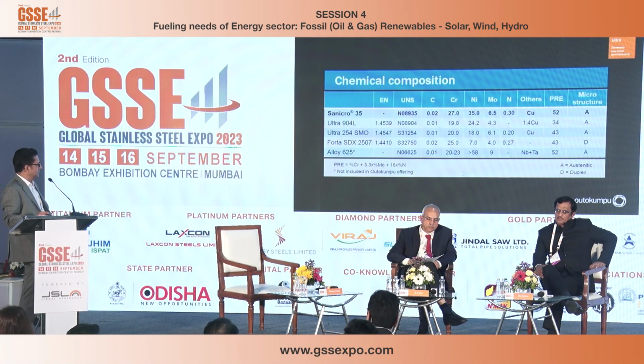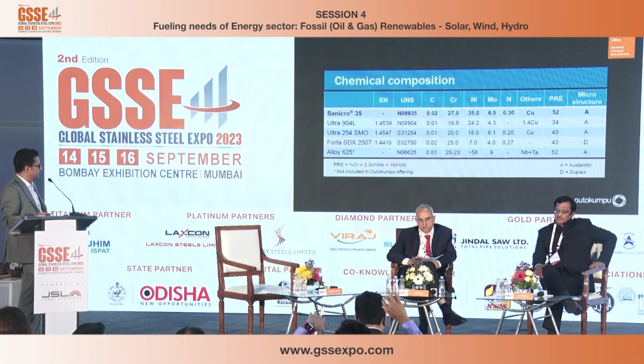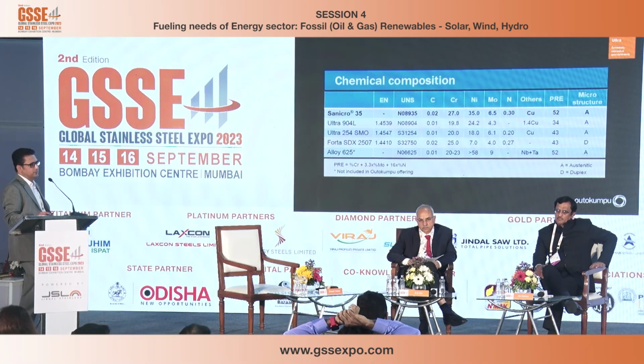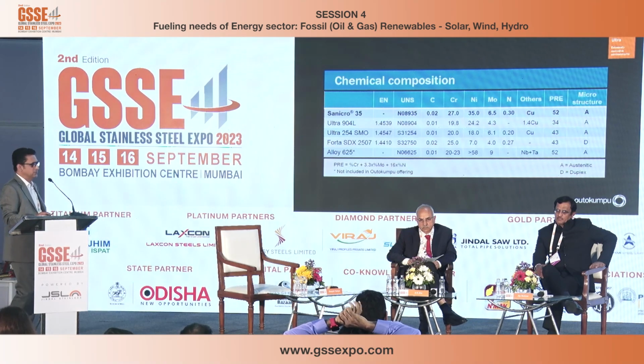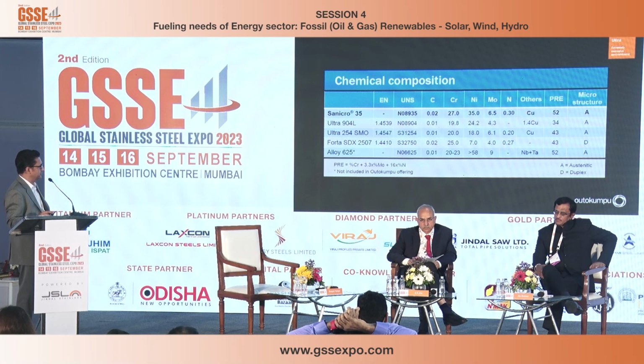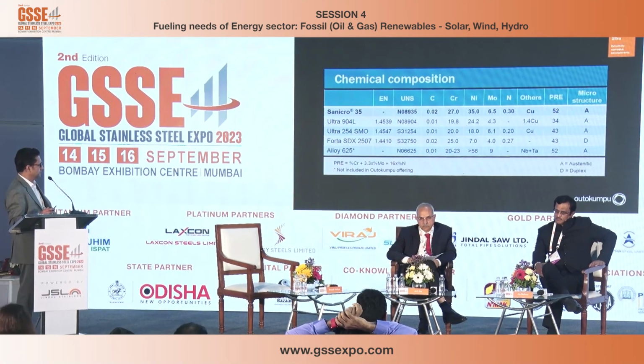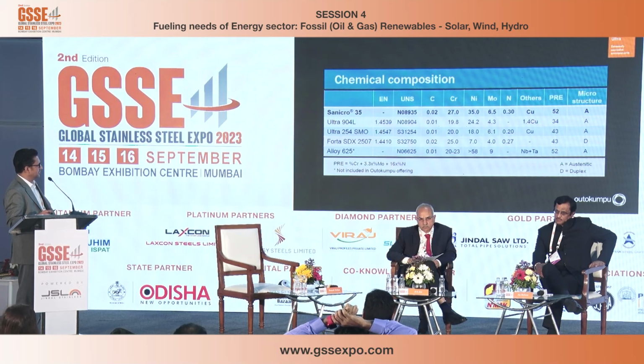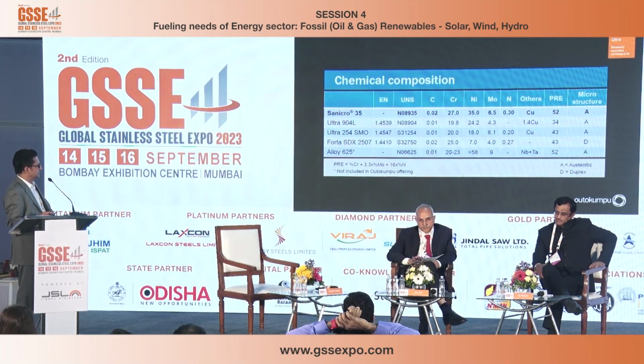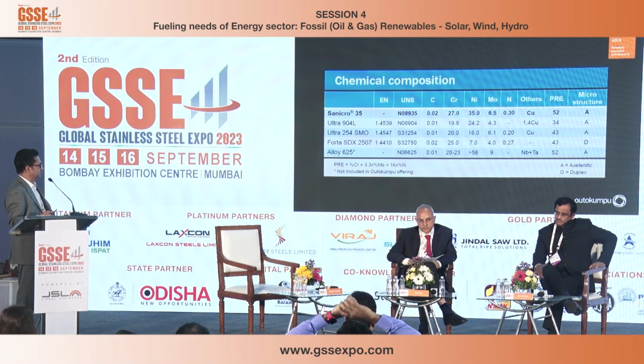This is the chemical composition. Let's try to compare it with alloy 625 on the bottom. Alloy 625 has more than 58% nickel, and what we have done over here is nickel has been reduced to 35, which means you have a lot of saving on the material cost, and the final product works out to be a cheaper one. We have reduced the molybdenum, so it is not much dependent upon the ferromoly cost, and both are austenitic. Some copper has been added, and chromium has been increased from 20-23% to 27%.